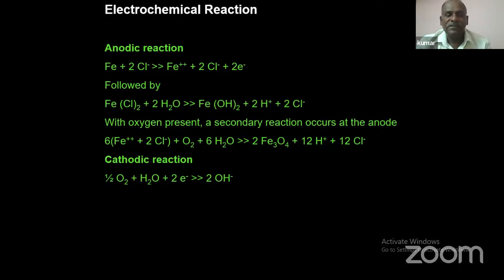How are the anodic reaction and cathodic reaction happening? That is the one given in the video. The chloride from the seawater, Cl minus, forms Fe plus 2Cl minus, with 2e minus electrons, and the electrons go to the cathodic reaction. The cathodic reaction is water with the electrons forming OH minus ions. So what happens initially is that FeCl2 forms, because once the electrons go, these two immediately couple. Then reacting with water, it forms Fe(OH)2, because this cathodic reaction also comes over there, and you will be getting Fe(OH)2.